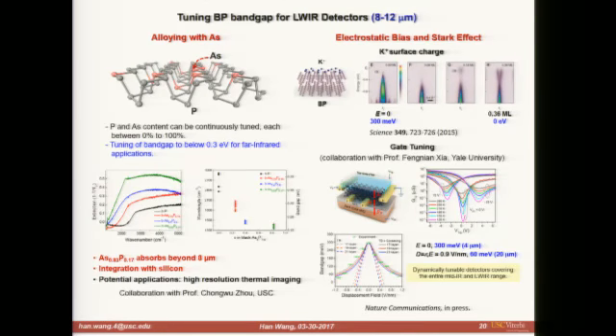So in our work, we've been working with our collaborator to demonstrate the same effect but through just electrostatic gating, just by building an electrode underneath. Through transport measurement and also some tight-binding modeling, we've been able to see that if we increase the electric field from 0 all the way to 0.9 volt per nanometer, that's the displacement field.